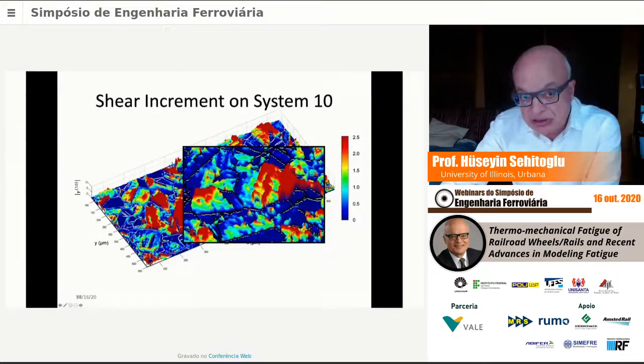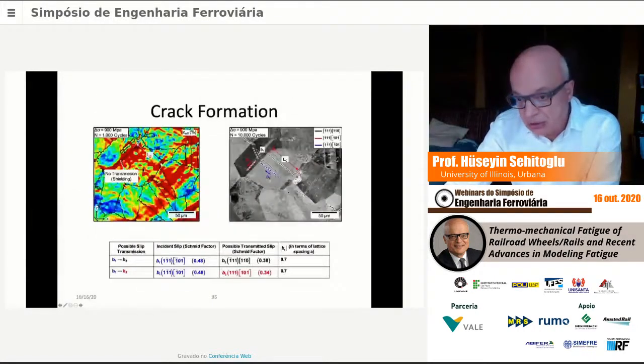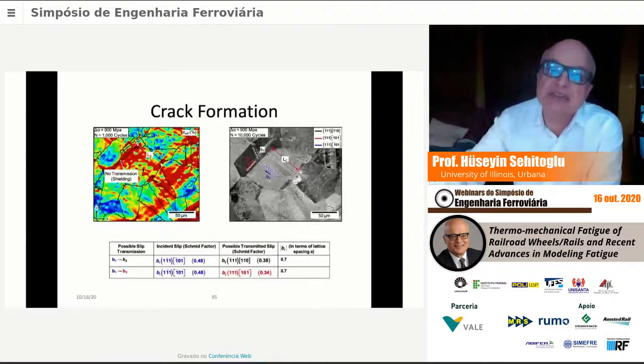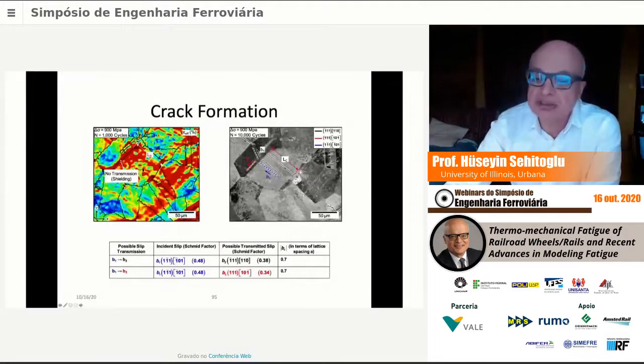This is shear increment on system 10. There are 12 slip systems in face-centered cubic materials. It's high here, but it cannot go into the next grain. So it's blocked. When it's blocked, there are very high stresses that are developed there. And this is conducive to cracking here. So that's what we're seeing there.